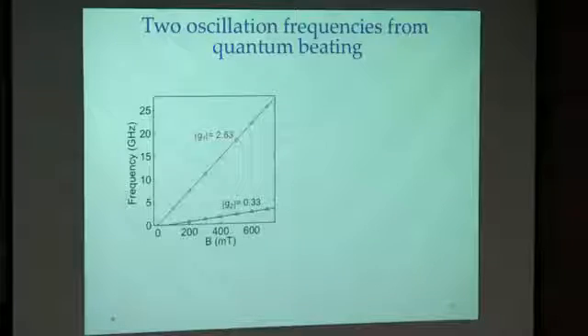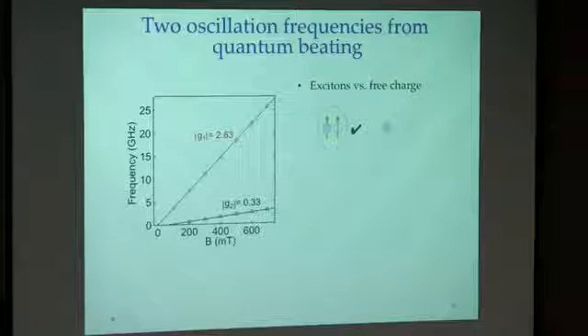Okay. Then the next thing, we need to figure out what the two frequencies are. So here I plot the two frequencies versus magnetic field. We can see that they are roughly linearly proportional to the magnetic field and go through the origin, but not quite. The lower frequency has a little bit of a negative offset here. So then we need to figure out what those two frequencies are. First, we would like to identify whether it's excitons or free charges. Like I just mentioned, we assume it's excitons, but it's not obvious at the beginning.